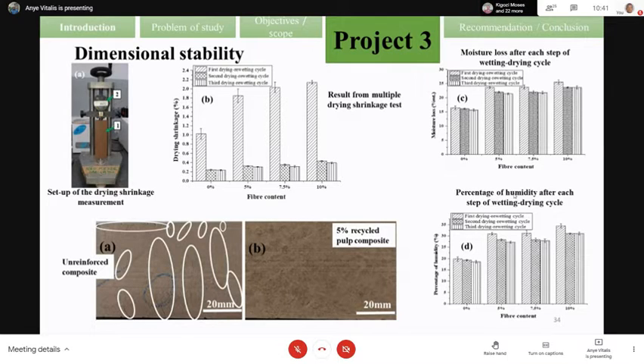The result is consistent with the moisture loss and also the percentage of humidity. This can be due to the fact that by applying one wetting and dry shrinkage, we already have a void between fibers and matrix. So by applying that shrinkage, you can have a precipitation of the further cement hydration, which can help to produce a hydration gel, which can help to densify the interface between fiber and matrix and will improve the adhesion between fiber and matrix.